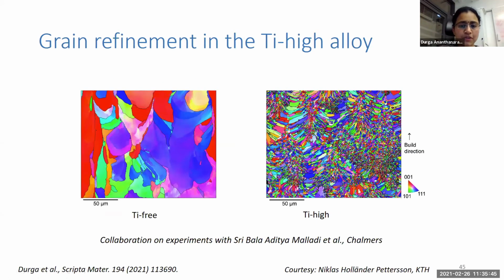So when we printed these two alloys and analyzed them, we find in the case of the titanium high alloy, compared to the titanium free, we also see a lot of equiaxed regions clearly. So the titanium nitride does seem to work. And this project is in collaboration with Chalmers, where they are doing a lot of printing and experiments for this study. So what's going on here?